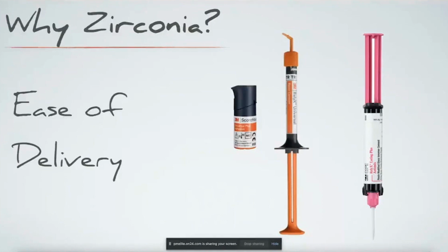No need to light cure with this system, which is really nice, because if you haven't thinned that bonding agent enough, and some of the ones that require light curing, you can be pooling that bonding agent on the surface and get inadequate seat of your crowns. But the fact that this bonding agent reacts with the RelyX Universal Resin Cement doesn't require any curing. I can simply scrub it in, blow it thin, add the RelyX Universal Resin Cement to my restoration, and seat it. And once these two come in contact, then the curing process will start. After that, I can use my light to tack, cure, and clean up.